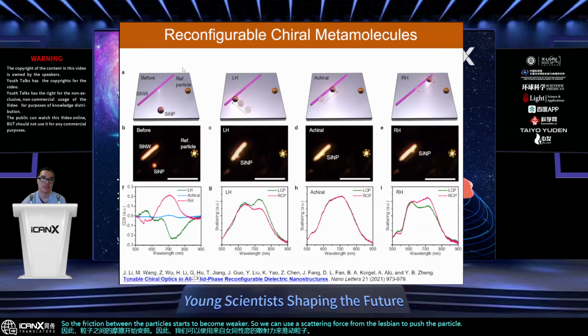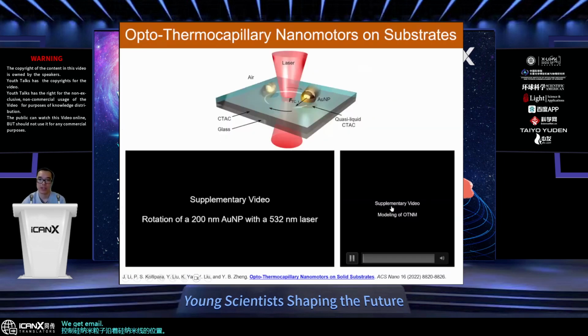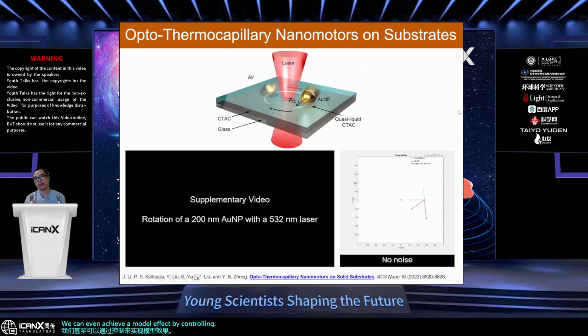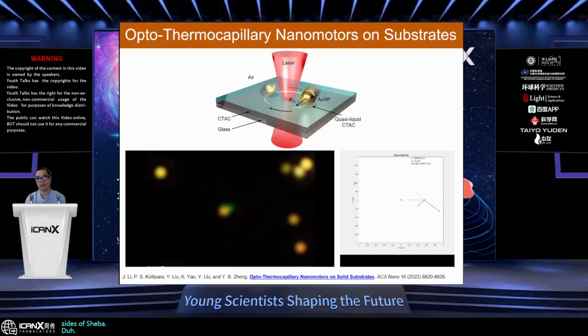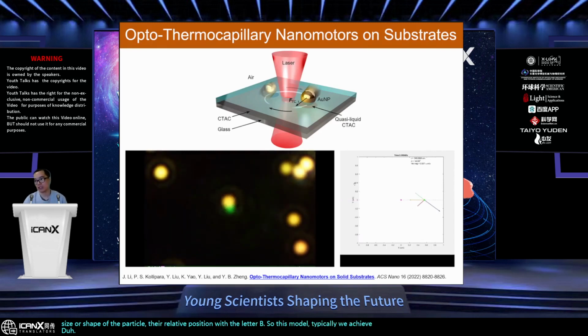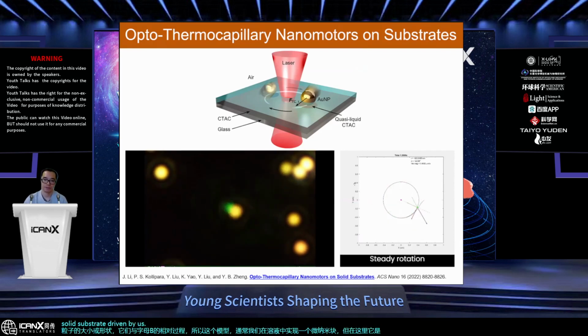For example, we have this silicon nanowire. We can use this method to push the silicon nanoparticles along the silicon wire. Depending on position, they show very different color responses. The very interesting optical property can be controlled by simply controlling the position of the silicon nanoparticle along the silicon nanowire. We can even achieve a motor effect by controlling the size or shape of the particle and their relative position with the laser beam. Typically we achieve a micro-nanomotor in solution, but here it's on the solid substrate driven by a single laser beam.